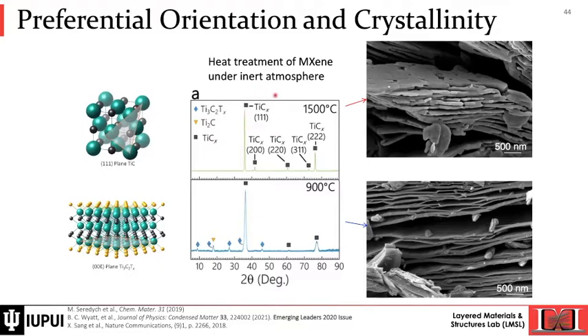That's why these diffraction peaks are a lot stronger, and it is not something that you see in a regular TiC. So by the use of MXene as precursor, we can design carbides and ultra high temperature materials with a unique morphology, with a unique texture that is impossible to do in a regular route of making these carbides.